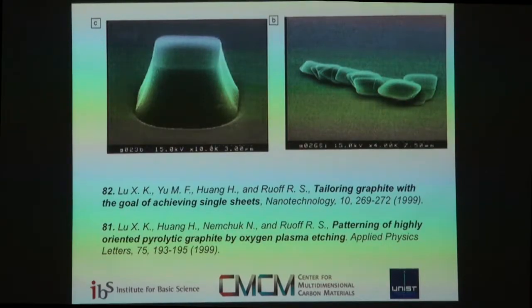But one thing we did do, and I'm proud of myself because I actually did this, because most of the time students and postdocs are doing everything, I rubbed the pillars very quickly with a silicon wafer, and then we looked with SEM, and they beautifully spread out in this manner, and you can see some are very thin, quasi-transparent in the center. We might call that multi-layer graphene now. We have to figure out exactly how thick it was. Another reason why this is probably worth revisiting is it gives you very well-controlled shapes, and then we could obviously pattern at all sorts of different length scales these days, including down to nanoscale.